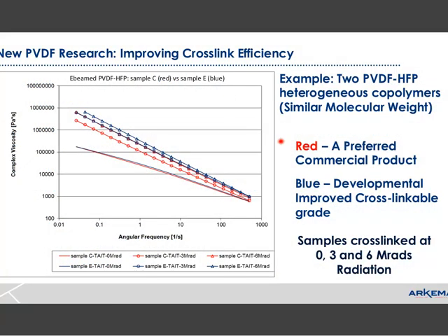This can be a hard slide to try to explain, and I'm going to do my very best. What we're comparing here, this is viscosity as a function of shear rate, and I'm comparing two products. The lines in red are a commercial product, and the lines in blue are a Developmental improved cross-linkable grade. The red grade is what I would consider a preferred or one of the best or premier products out in the market, and the blue is something we're working on to try to improve that.